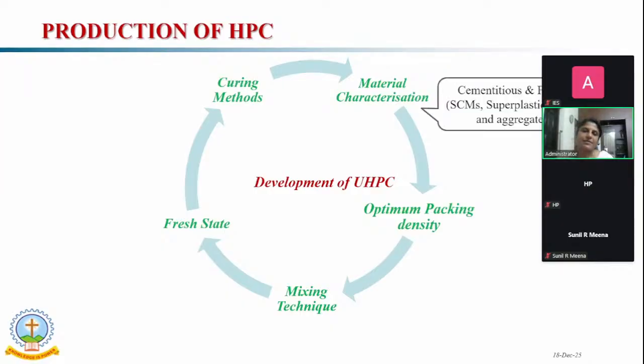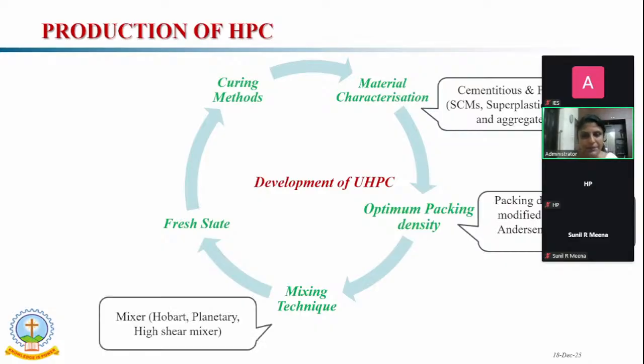In the case of material characterization, we have considered the binders and fillers. Fillers are used to improve the particle packing density, and the fibers are to get the ductile behavior. Then some supplementary cementitious materials are tried, along with superplasticizers, fillers, fine aggregates, and the fibers. To get the optimal particle packing density in the laboratory experiment, we have considered the Puntke test. And by using software, we have considered the EMMA software that is based upon the modified Andreasen and Andersen model. The EMMA software is developed by Elkem.